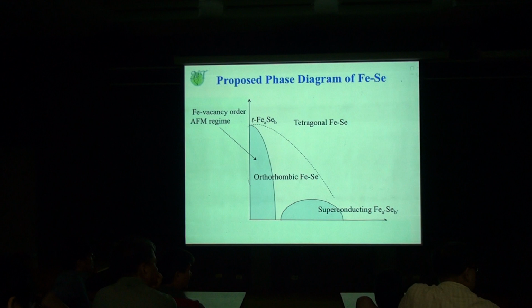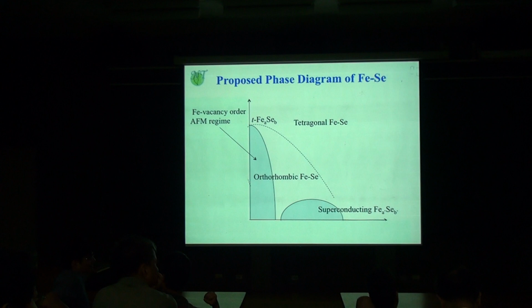True, but in my own view, it doesn't have to be a single layer to make that higher TC. The dimensionality in terms of the unit cell, one layer or two layers, is not the key. It just happens that it's probably easier to use a single layer to stabilize that and get a higher TC. So we probably don't need another dimension. When we study high TC, one layer, two and three layer systems, the dome will be a similar shape, but with a different optimal value. You can tune the optimal value by changing the dimension, but the dome shape and the mechanism stay the same.